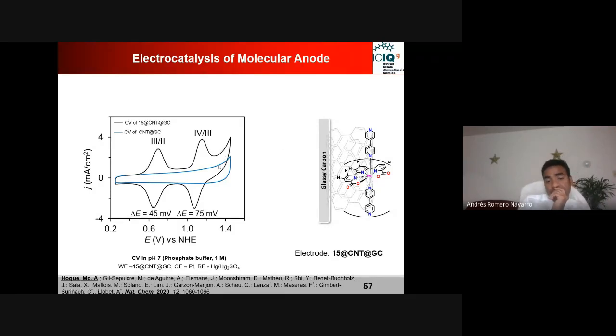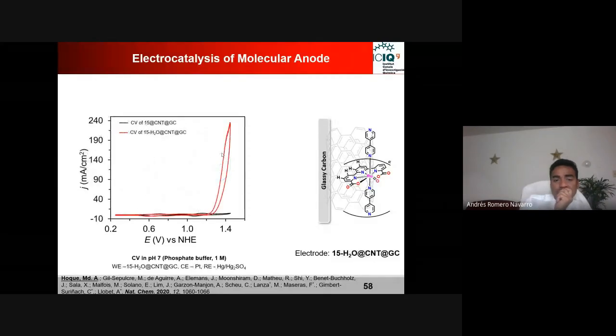So the real catalyst is that you need to apply the potential here, and then you will form a completely new compound. And that is actually the active catalyst, and that is exactly what we found here. So we apply the potential here, and now we see that we are forming some new compound upon applying the potential. And then we are doing the cyclic voltammetry.